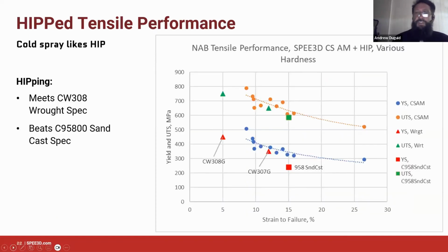So here's the punchline of things. What we're looking at here is another one of those plots, with the yield and the UTS plotted above one another on the Y-axis, and then the strain to failure locating both those points on the X-axis. This is pretty much our entire data set for a whole battery of tests that we did, predominantly for different heat treatment conditions, different solutionizing and different age procedures. Obviously what that's doing is driving the hardness of the material to different values. Any metallurgist will recognize that it doesn't really have a name. I just call it a metallurgical trend, where you're trading off hardness against elongation, and you're getting that gentle southeast trend there.